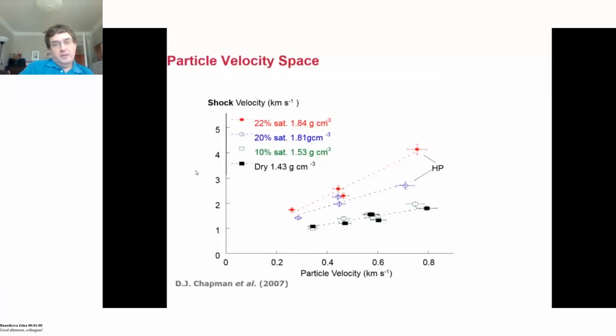One thing that we found particularly interesting for the shock response of granular materials was that if we looked at shock particle velocity space, we discovered that having dry sand, and here it is using the black squares, you have a line which is fairly flat compared to other systems you can find, and then adding 10% water, so the white squares there, basically had very little difference to the shock compression of the material. When you got to 20% saturation, so this is the white circles there, you can see you had a marked difference there. There's definitely made a difference.